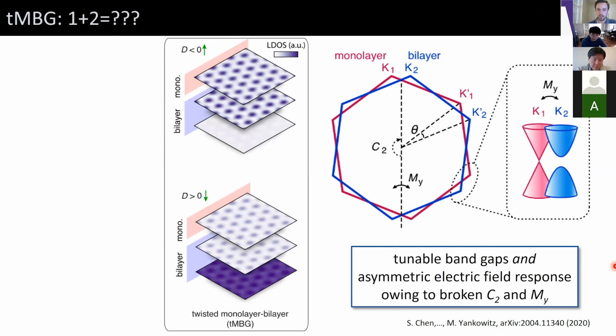So to illustrate this and to try to build some expectation for what we might expect, we can calculate the local density of states. So basically how the charge arranges itself on each of the 3 graphene layers in the heterostructure. So the bottom 2 are the bilayer, the top one is the monolayer. And these are very different now as a function of the sign of the electric field. So for electric field negative, which by convention we define as pointing from the bilayer towards the monolayer, the local density of states strongly localizes on the 2 graphene layers at the rotated interface